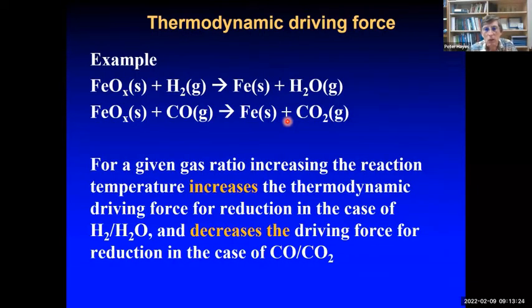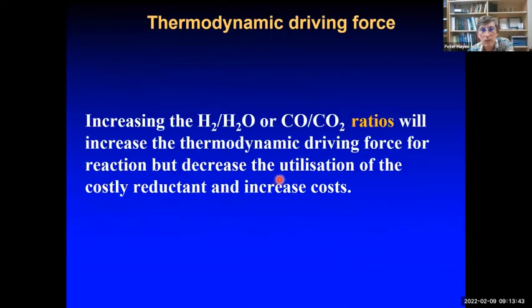And here I'm just repeating that statement. So for a given gas ratio, increasing the reaction temperature increases the thermodynamic driving force for the case of hydrogen-steam, but decreases it in the case of CO-CO2. And increasing hydrogen-steam ratios and CO-CO2 ratios will increase the thermodynamic driving force for reaction in both cases. But what we find is the utilization of the gases will be decreased because we're having to use more of the reductant, and that means increased costs.